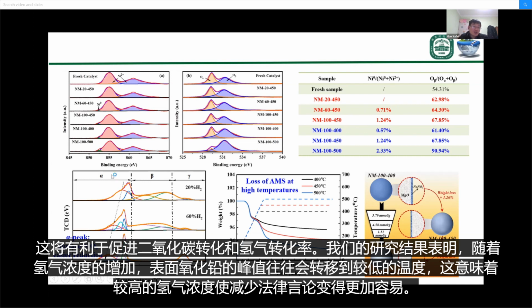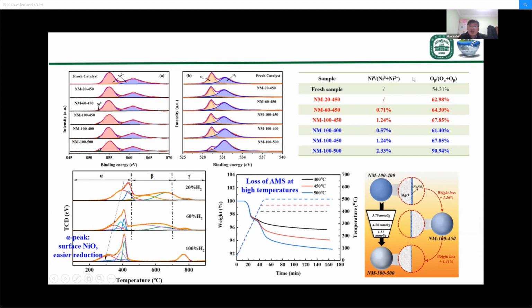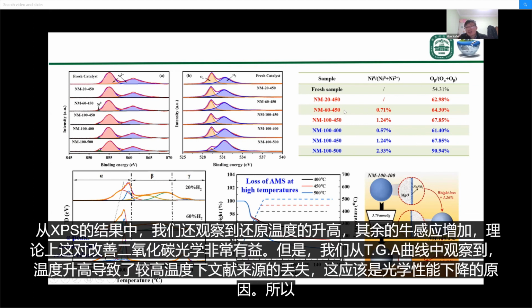And hydrogen TPR results indicate that with increase in hydrogen concentration, the alpha peak for surface nickel oxides tends to shift to lower temperature, which means that a higher hydrogen concentration makes the reduction of the nickel species easier. And from the XPS results, we also observe that with the increase in reduction temperature, the ratio of the oxygen vacancies increases, which is theoretically very beneficial for improving CO2 uptake. However, we observed from the TGA curves that a higher temperature has induced the loss of alkali salts, and this should be responsible for the decline in the CO2 uptake.